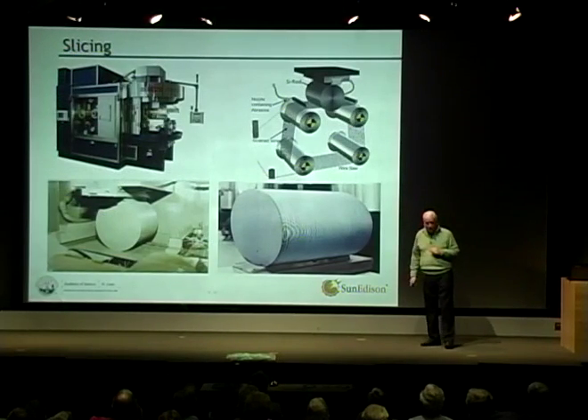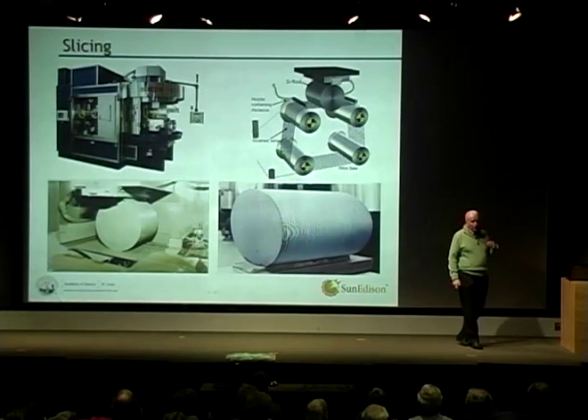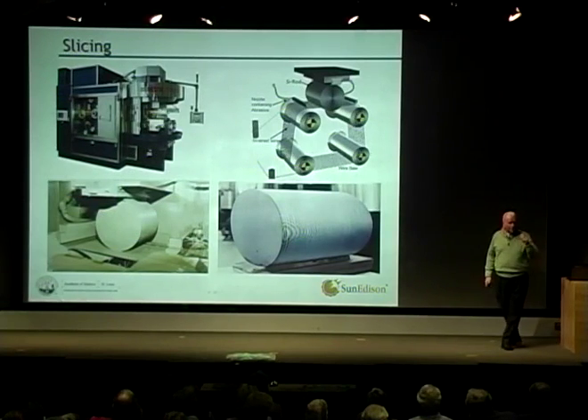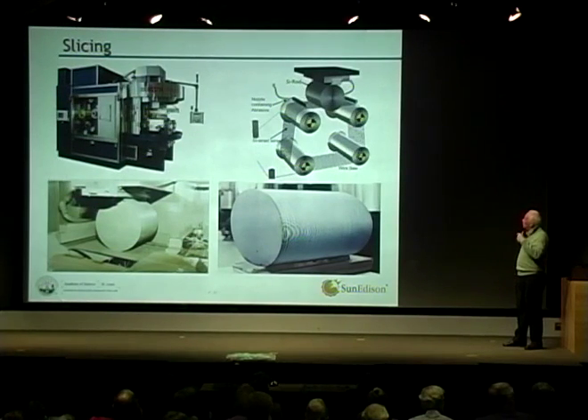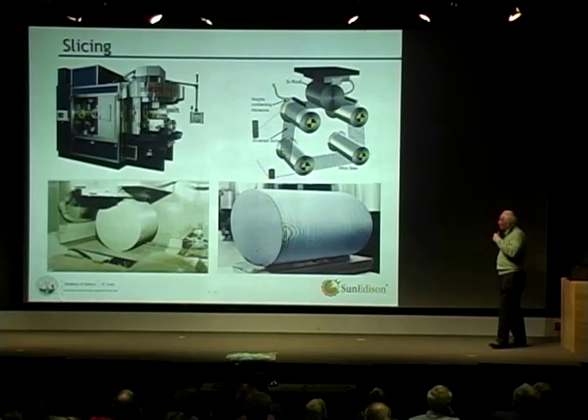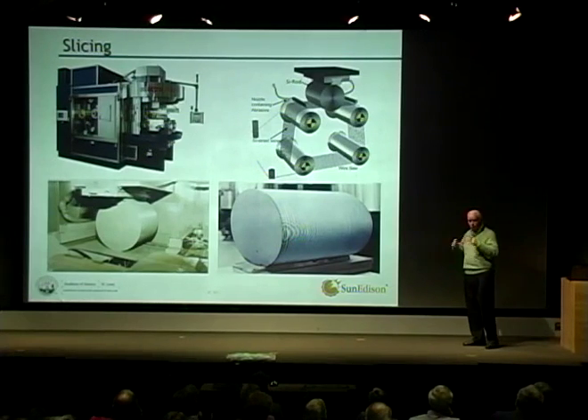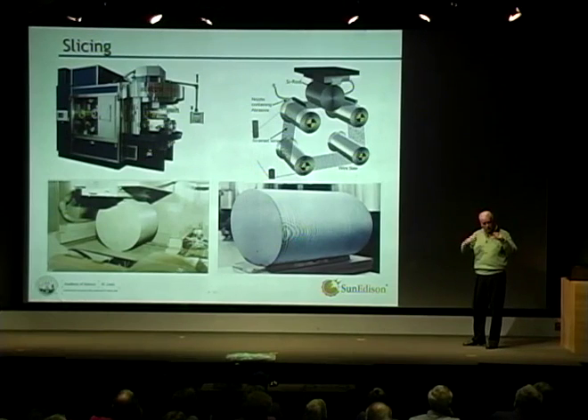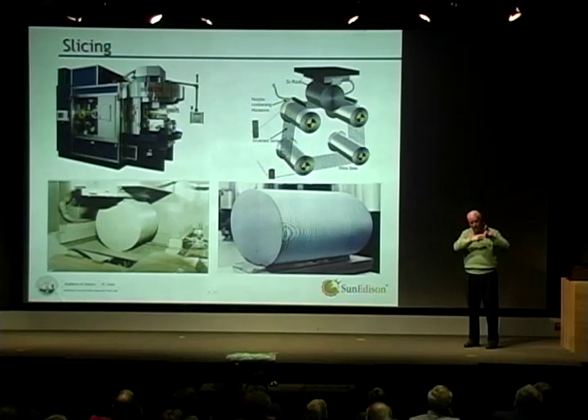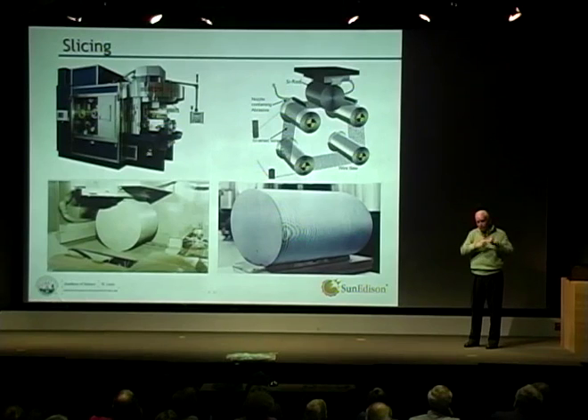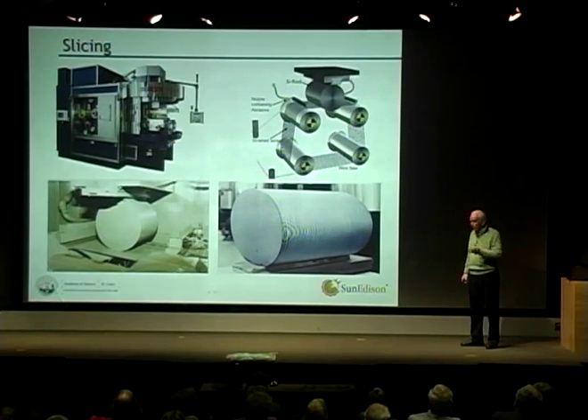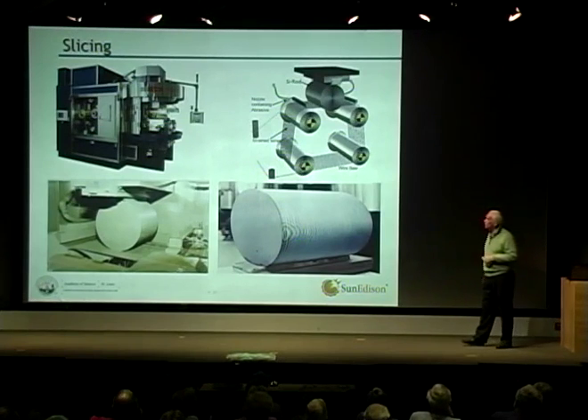Okay, so in slicing, they used to use an internal diameter saw, which is like a big washer, and we put the silicon through the middle of the washer, and the inside rim of the washer was coated with diamonds, and that would rotate at high speed, and we cut one slice at a time. They don't do that anymore. They use what's called a wire saw. It's a bit like your grandmother's egg slicer, except it's one wire instead of lots of individual wires.